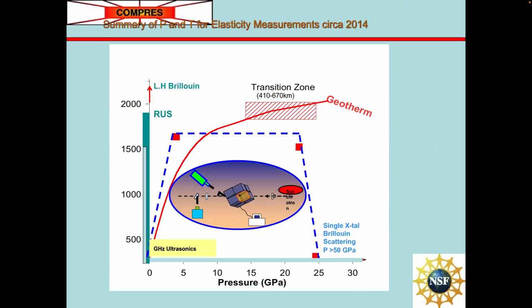This is a summary from about 10 years ago of what these various experiments could do at various pressures and temperatures. If you look along the vertical axis, resonant ultrasound spectroscopy can measure to very high temperatures, most frequently at room pressure. The Brillouin scattering techniques that were adopted and pioneered by Don Weidner at Stony Brook can reach incredibly high pressures, most often at room temperature. They go well above 50 GPa. The gigahertz ultrasonics, which we've been using at Stony Brook and ANU to measure the sound velocities as a function of simultaneous pressure and temperature, can now reach temperatures above 1500 K and pressures in excess of 25 GPa.